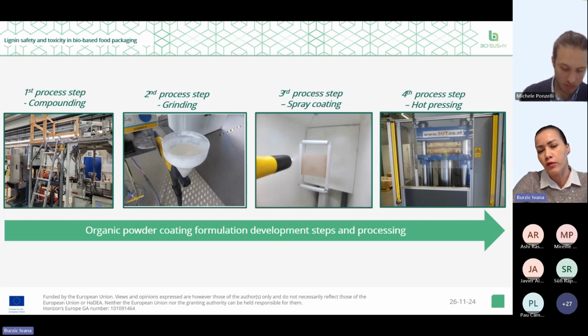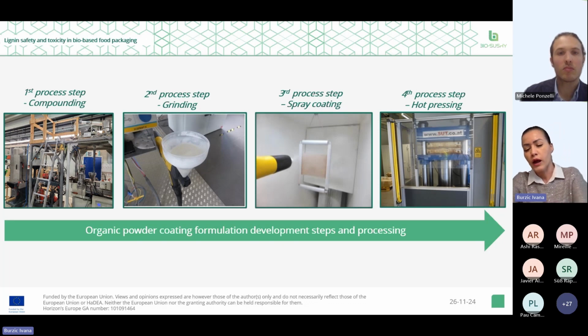And then the third step is basically spray coating to apply such formulations on a paper. That step is followed by hot pressing, where we basically do film formation on paper by increasing the temperature according to the material being used as a coating.